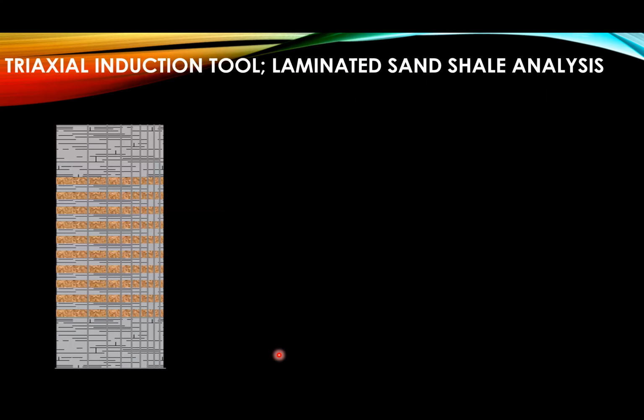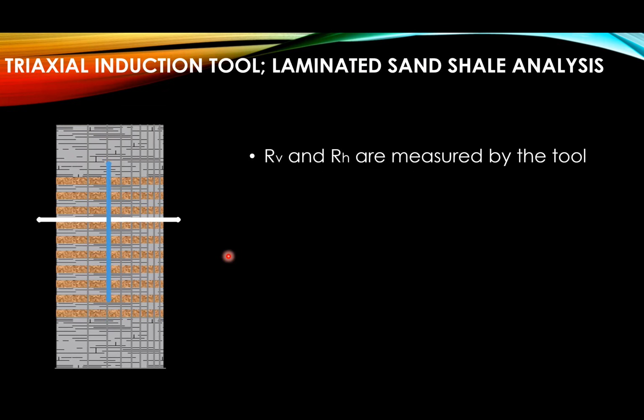Okay, now looking into the laminated sand-shale volume. Let's consider this as a block of rock, where all the gray colors indicate the clay, and then you have the sand coming in between. A conventional resistivity measurement generally measures like this, right? It's a lateral measurement. But when you use the triaxial tool, it has a vertical component as well. So we now have Rv, the vertical resistivity, and Rh, the horizontal resistivity, measured by the tool. That's an input into the laminated sand-shale model. And apart from the vertical and horizontal resistivity, we can also calculate a formation dip from this tool as well.